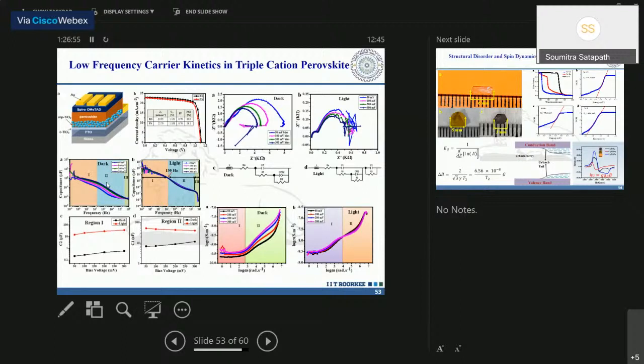So this area is affected by the bias. That means that whatever charge carriers have been generated in the triple cation device, that is still going to the interface in the intermediate frequency or low frequency. In the intermediate frequency, the increase is quite high, because at the low frequency region, in addition to the electrons and holes, ions are also contributing as charge carriers, and that's why ion movements in addition to electron and hole movements give rise to the high value of the capacitance. But in the high frequency region, that value is less. So even in the triple cation device, there is some amount of ion migration, but not at high frequency, only at the low frequency region, keeping us room for developing this device further.